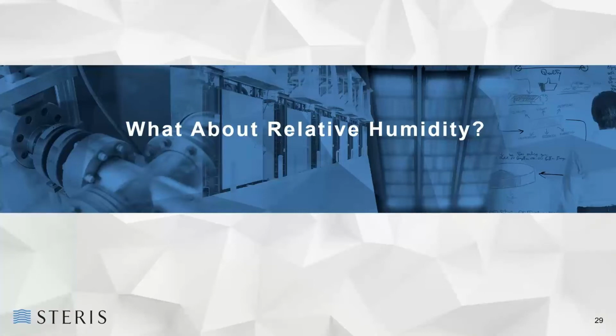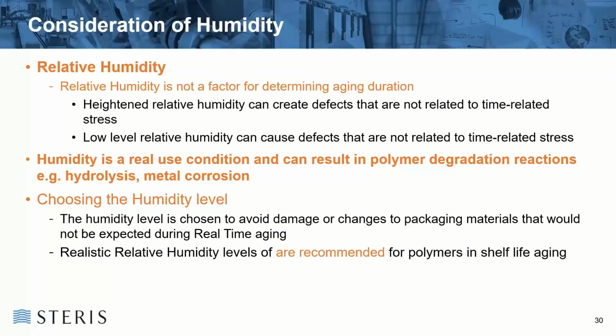In relation to relative humidity, while it's not a factor in determining the aging duration, especially in the calculation for the Arrhenius reaction rate, it is a real life factor, and that has to be taken into account in relation to, say, the likes of polymer degradation, so like the likes of hydrolysis or corrosion in metal. It should absolutely be in there. Or like the example I gave earlier, the shipper boxes actually falling apart.